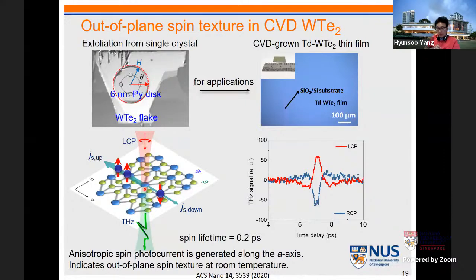To look at those, we use CVD WTe2, it's wafer scale. So now we can make many devices. Also, we can look at much larger scale measurements such as terahertz, which has a beam size of sub-millimeter, for example. So we can excite this material with circular polarized light. Then circular polarized light will couple with either spin up or down, depending on the polarization direction. Then the spin current will move in only one direction. For example, up spin will move in the minus a direction, but down spin will move along the a direction.